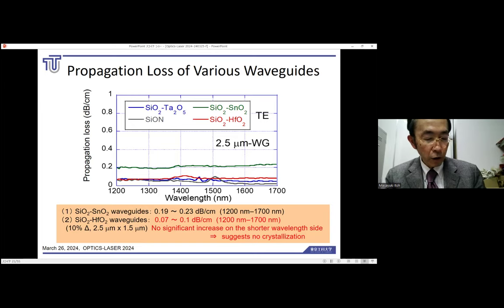The propagation loss does not increase on the low loss side, suggesting that crystallization has not occurred. The silicon dioxide, hafnium dioxide waveguide is promising as an extremely high delta waveguide because a low loss waveguide can be realized under high compressive stress.